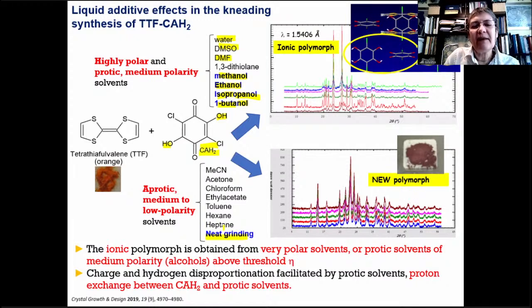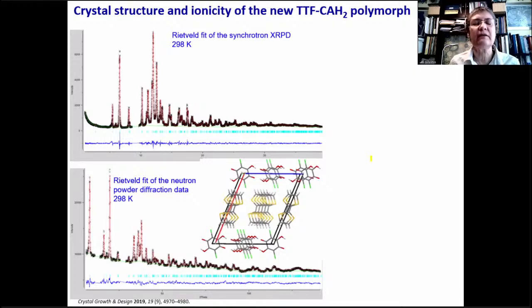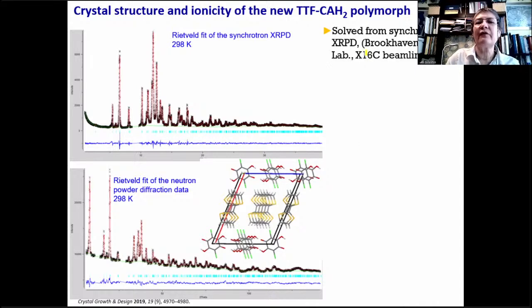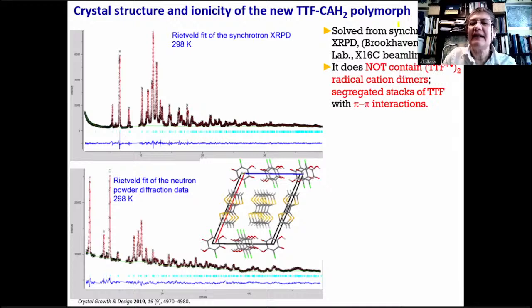And this is obtained with heptane, hexane, toluene, ethyl acetate, chloroform, acetone, and acetonitrile, which are low to medium polarity additives. So again, one of those additives was used to prepare single phases, or almost single phases, of this charge transfer complex. And the crystal structure of this material was solved from synchrotron X-ray powder diffraction data. And here is the Rietveld fit. It does not contain these radical cation dimers of tetrathiafulvalene, but it contains segregated stacks of molecules, shown here, which are held together by pi-pi interactions.